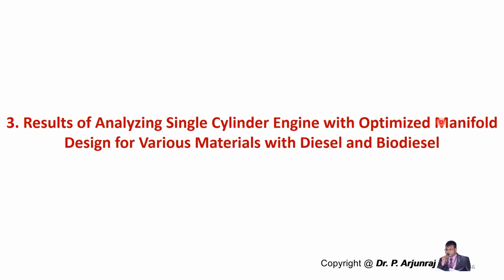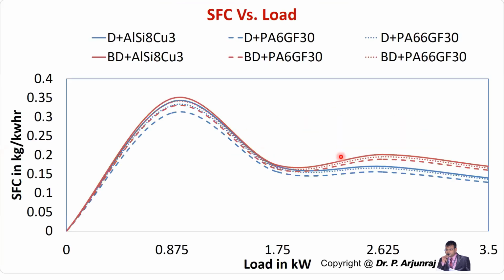And the results of analyzing single cylinder engine with optimized manifold design for various multiple materials with diesel and biodiesels. So here what I have done is I've taken diesel and also biodiesel as a fuel, and I have analyzed the performance and emissions of PA6 with glass fiber 30, and also PA66 with glass fiber 30 and aluminum material. So the findings here reveal that the BSFC for PA6 with glass fiber 30 is comparatively less when compared to that of the other PA66 and also aluminum. And this is because of the material property of the air intake manifold, which is causing